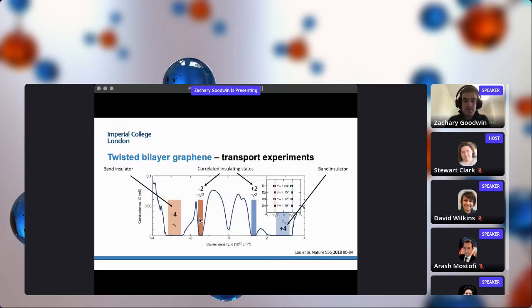And in 2018, it was in fact found on fabricating one of these devices, magic angle twisted bilayer graphene, performed by Yuan Cao at MIT. They found there was an onset of correlated phases. So their transport experiments basically found that at charge neutrality, they do in fact find features consistent with a Dirac cone. And upon removing 4 electrons or adding 4 electrons to the system, they find strong band insulating features as well. But in addition to these features, they also found correlated insulating states upon doping the system with either +2 or -2 electrons.